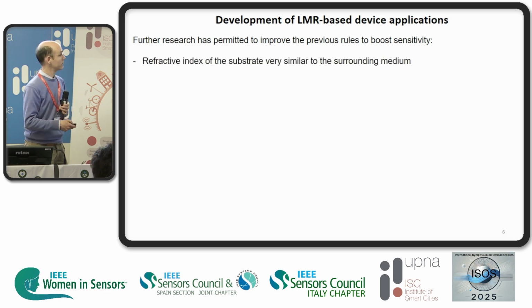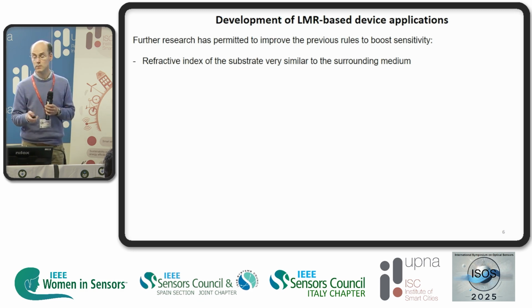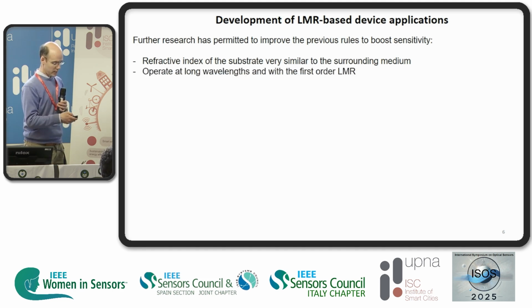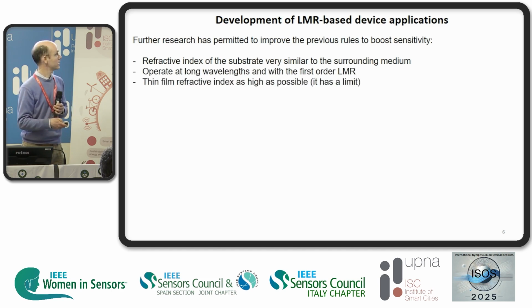And the first rule that we can consider is that the refractive index of the waveguide, of the substrate, must be very similar to the surrounding medium. If we approach both parameters, we get very sensitive sensors. For instance, with side-polished fiber, with refractive index very similar to water, the sensitivity is increased a lot, to operate at long wavelengths, and with the first order LMR we observed previously.